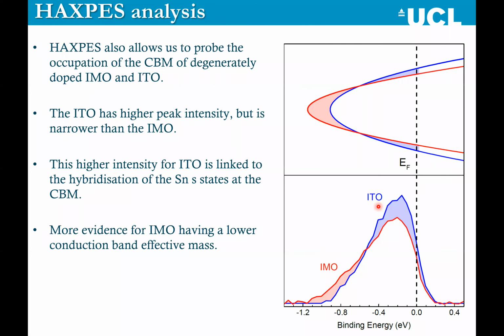What HAXPES also allows you to do is to zoom in on the bottom of the conduction band and look at the occupation of the bottom of that conduction band. And of course, the thing you have to remember is that the density of states of a system is basically the integration of the band structure. So the fact that the ITO has a higher peak intensity, but narrower than IMO, means that it supports IMO having a much curvier, more diffuse conduction band than ITO, which has a broader conduction band. So this is again more evidence for IMO having a higher mobility.